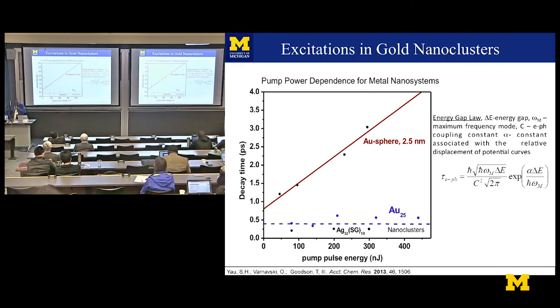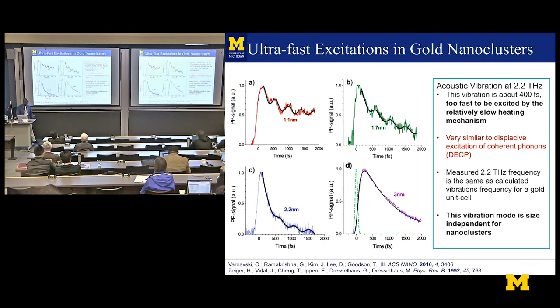We were saying, well, what if we were to try to see more closely what is happening inside those 13 atoms in the core? So Oleg Varnavski, who's a research professor in the group, did a very interesting experiment in which we used the so-called transient grating. Basically, it's a pump probe type signal in which we read a grating off the absorption of this system. And once the absorption grating disappears, that means the interaction between the phonons is gone.